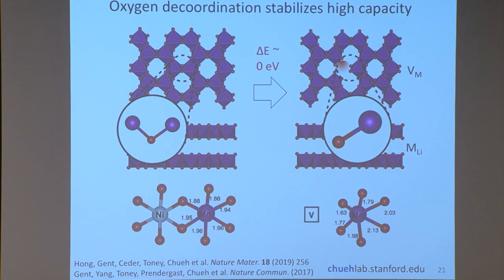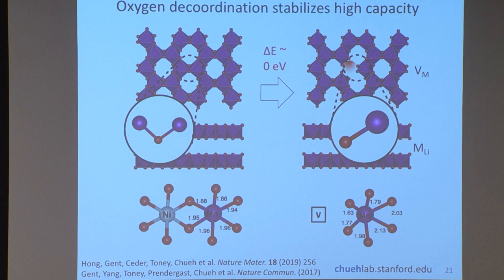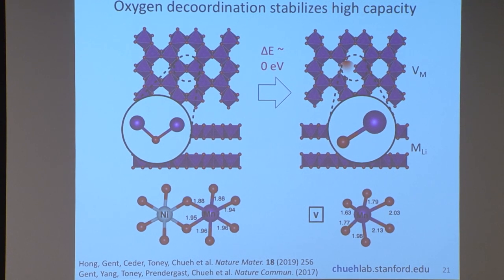For example, this defect formation energy is very contingent upon which metal you have. So if you understand the defect formation energetics, then you can maybe choose your composition to create this type of favorable defect. In this case, you want this defect so you can hold on to the oxygen. So I would say the short answer is you can go through processing, but you have to keep it there. So this relies on the metastability of these defects under the temperature at which you're operating your device. But you can also think of creative ways, such as substitution and other compositional methods, for keeping the defects.